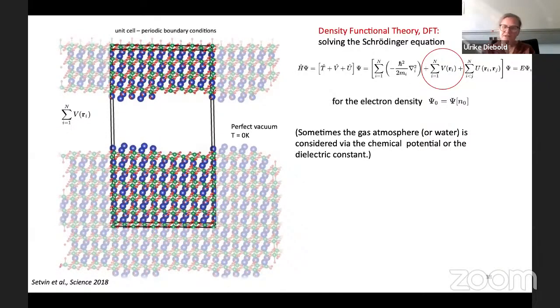And then in DFT, what one can do is, for example, think of water and look at it explicitly, like in these molecular dynamics simulations, but very often people just put in the dielectric constant, like in VASPsol, right? Or you can put in the gas atmosphere, the temperature, with the chemical potential. But really, that's the essence. It's just like an offset, a straight line, essentially. What you calculate is the surface energy of this particular setup, and then you take into account the dielectric constant or the chemical potential. But really, that's the essence, right? So what people calculate is what we measure.